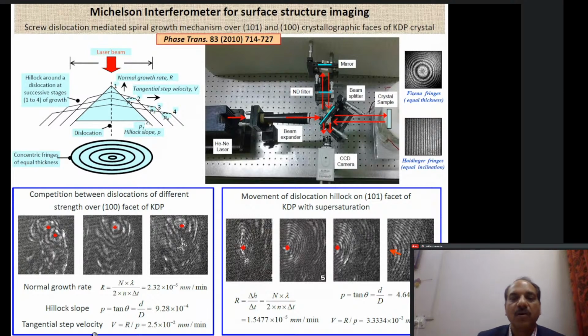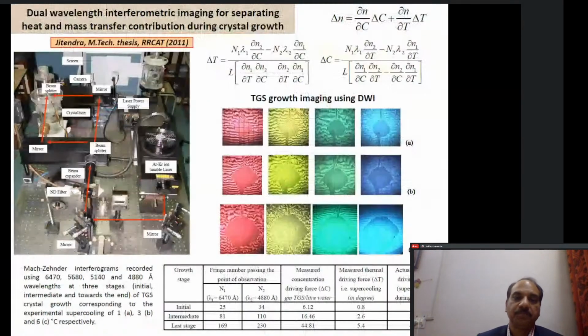And this is how we were able to record the movement of dislocation hillocks on the 101 facet of KDP with saturation. Similarly, if there are multiple sources of dislocations, we were able to see the competition between dislocations of different strength over the 100 facet of KDP. We also were able to quantify the normal growth rate, the slope of the hillock generated by the screw dislocation, and the tangential velocity of the steps created by that screw dislocation. In this way, we were able to quantify what was happening on the surface of the growing crystal in a very, very microscopic manner.